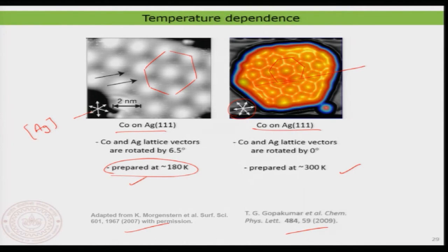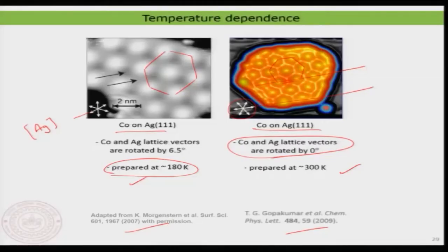So, that means in this particular case, the second example, the Moiré lattice and the silver lattice, you can see they are actually having no rotation with respect to each other, and that is what is written here, that the cobalt lattice and the silver lattice are actually aligned with respect to each other. But when you look at the case of the cobalt on silver 111, this particular example, you see that this is actually the super lattice, and the silver lattice is a bit tilted with respect to each other. Of course, it is not that obvious in my drawing, but they are actually having a rotation, and that rotation is about 6.5 degrees.